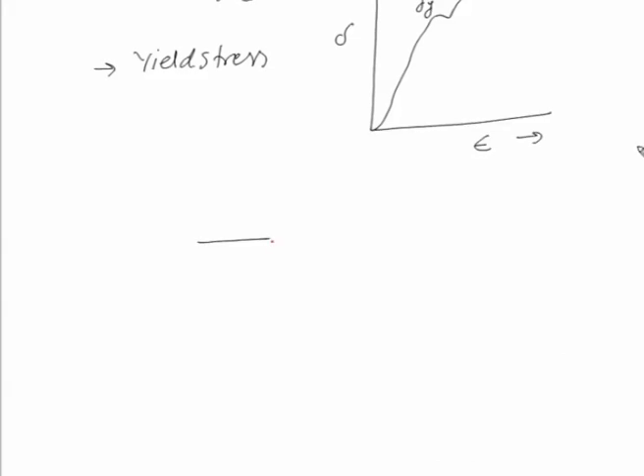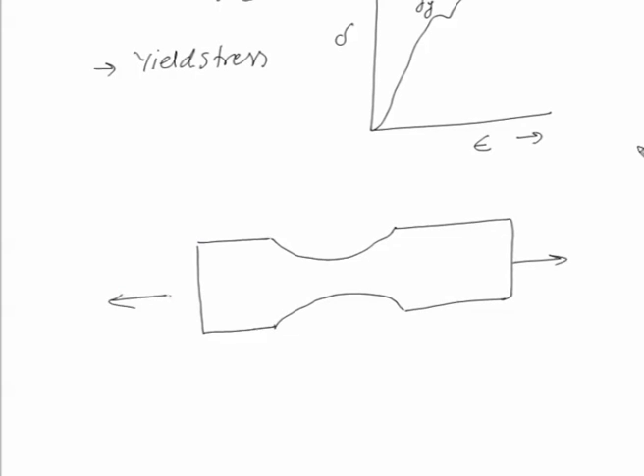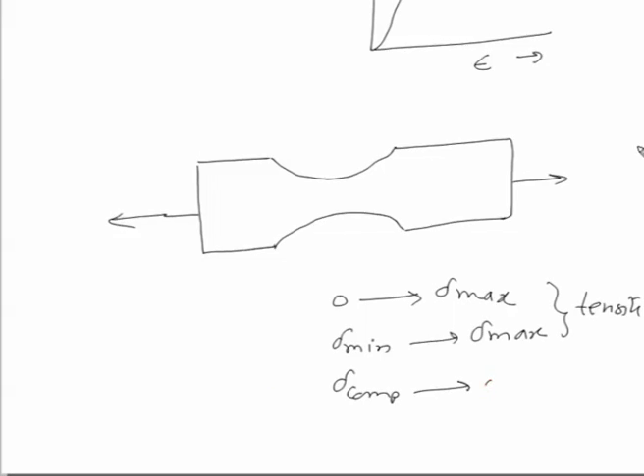So, another specimen, say of reduced radius cross section, will be developed, and this reduced cross section will then be subjected to the fatigue test, say in the case of axial loading. Depending upon the kind of stresses to be developed, ranging from say 0 to some maximum, or some minimum to the maximum. All these are of tensile kind, and then these can be minimum compressive stresses and maximum tensile stress; their values can be identified. This is how we identify the kind of stress and the maximum stress to be applied, and based on this we apply the loading conditions.